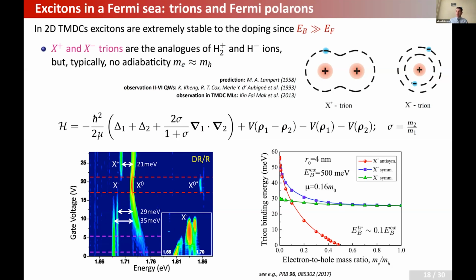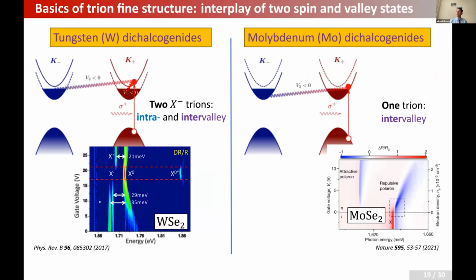So actually, it is not that easy, and there was a lot of debate in the literature how to describe this system properly. The point is that, of course, an exciton can bind with any electron in the system. Before I go into this detail, I will quickly tell you that depending on the transition metal, whether it is tungsten or whether it is molybdenum, there could be just a single trion line or a trion doublet. Because, for instance, in the case of tungsten, you can have both intra- and inter-valley interactions. So you have in principle two trions. The two electrons are in the same valley but with different spins, and the two electrons are in different valleys but with the same spins, and you can typically see a doublet here.